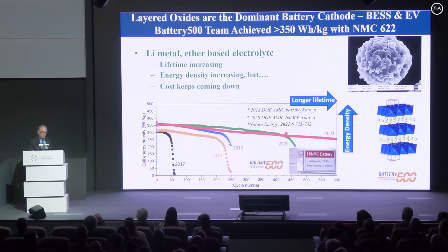So we have what we call the Battery 500 Consortium in the United States. Again, don't worry about the specific numbers here. The goal, Battery 500, means you want 500 watt hours per kilogram in a commercial cell, as compared to about 200 today. And just look at that plot on the left-hand side. All you need to look at is that over the last 5 years, we've moved from about 50 cycles to over 600 cycles. At the same time, we've also increased the energy. And this is what this consortium is aimed to do.